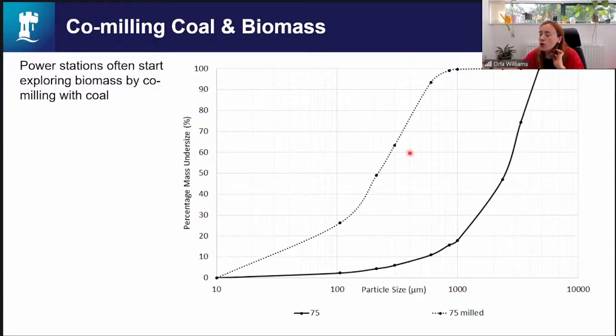We've also been looking quite a bit at coal and biomass. As I mentioned, we used to be a coal-intensive research institution. However, a lot of our research is helping other countries that are only starting on that transition to understand the issues that they have. So, for instance, we've been working with Australia, Colombia, and India on looking at co-milling. That's where you have, say, 90% coal and you add 10% biomass. This can often lead to issues because you've got two very different materials and you're trying to mill them at the same time.